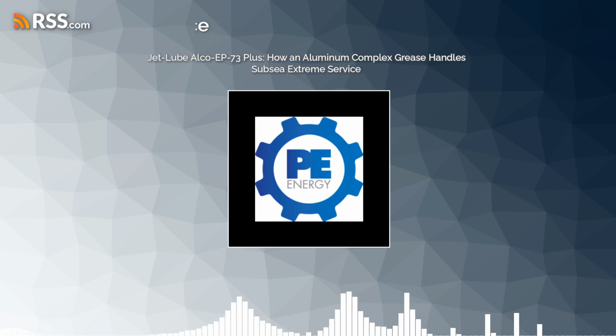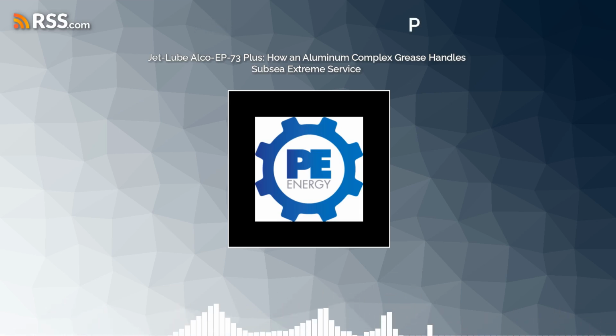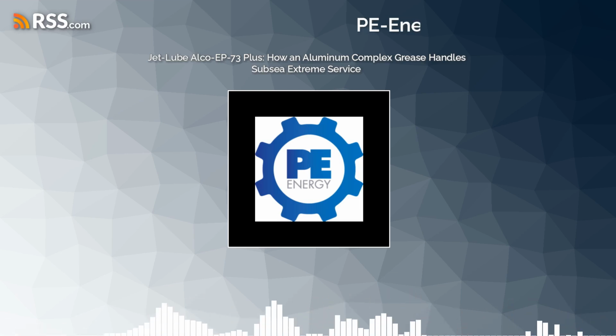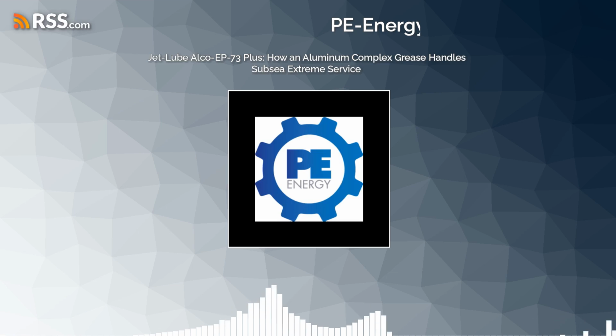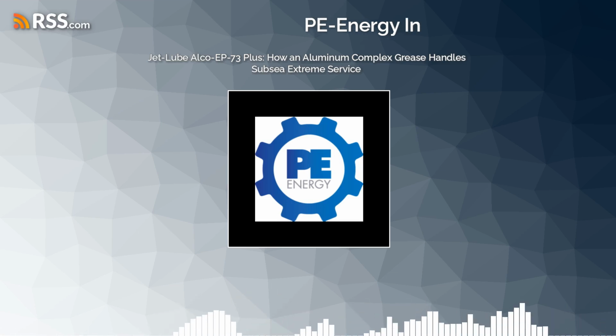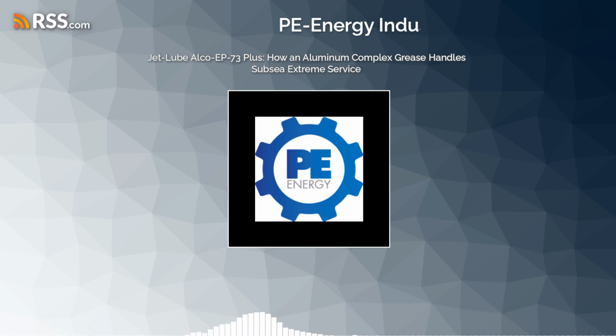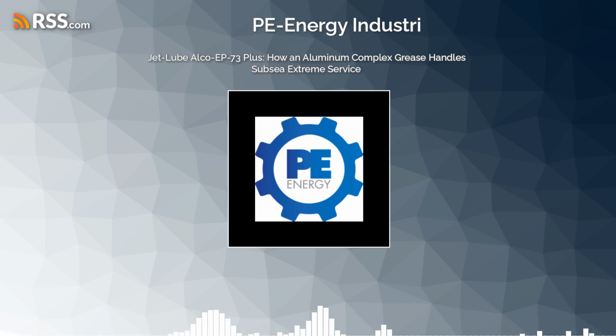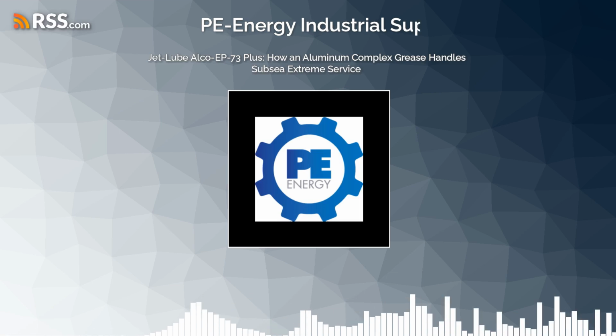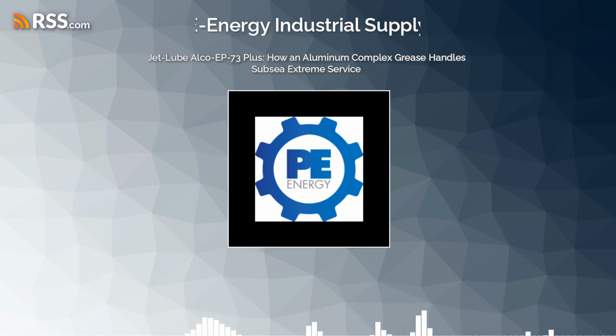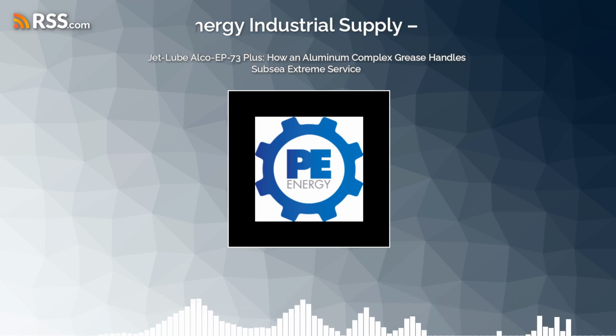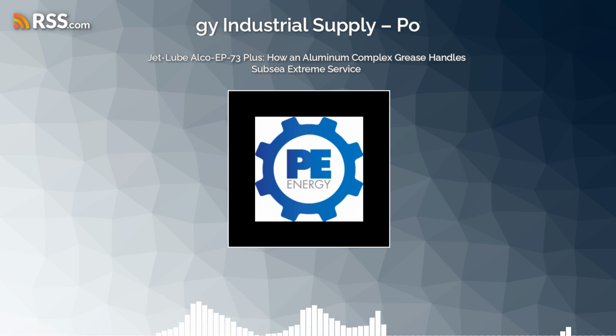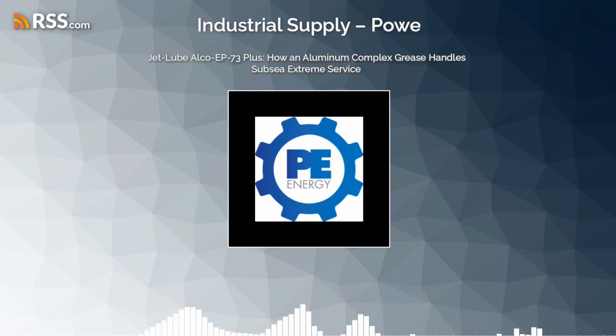Right. They put a sample of the grease into a sealed steel chamber, which is the bomb, and fill it with pure oxygen under high pressure. Correct. If the grease is chemically reactive and prone to oxidizing, it will physically consume the oxygen gas from the air, which causes the pressure inside the chamber to drop. Which means it's breaking down. Exactly. So a pressure drop of less than 5 psi over a full 100 hours of exposure means this grease is essentially ignoring the oxygen. It refuses to break down.